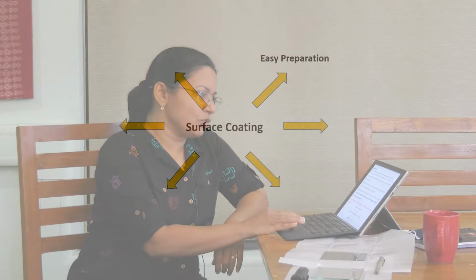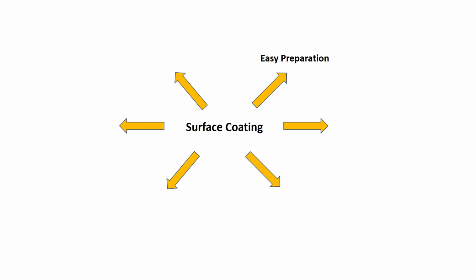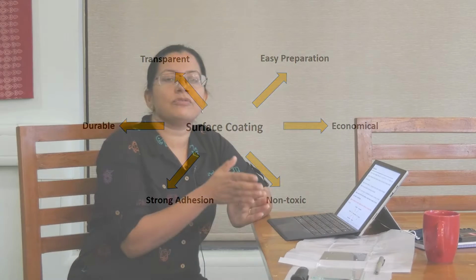So this requires synthesis of a surface coating that can effectively inactivate the microbes. The surface coating needs to be prepared easily, should be economical and non-cytotoxic, should have strong adhesion with the substrate, so that means it should not come out from the substrate easily, should be durable, and more or less it should be transparent, because if it is transparent then it would not compromise the aesthetic or design aspect of a particular material, and then it would be easily adopted by the customer or end user.